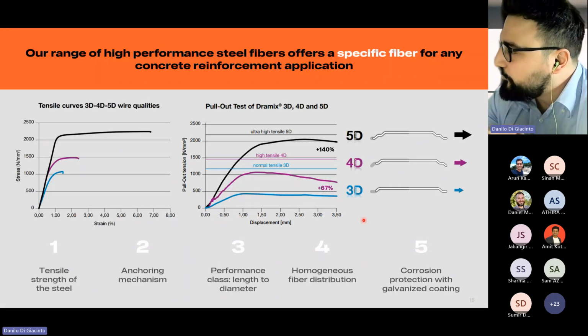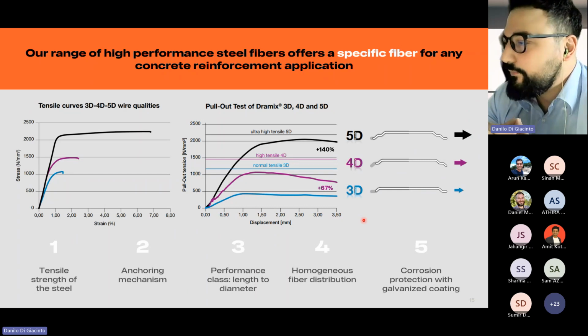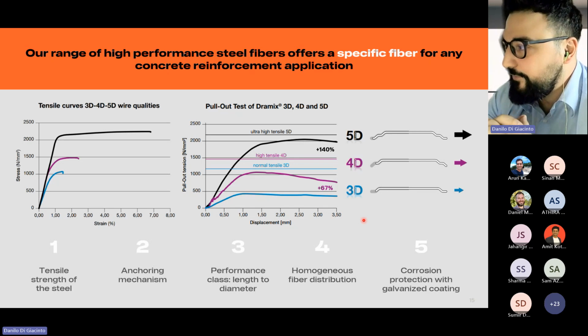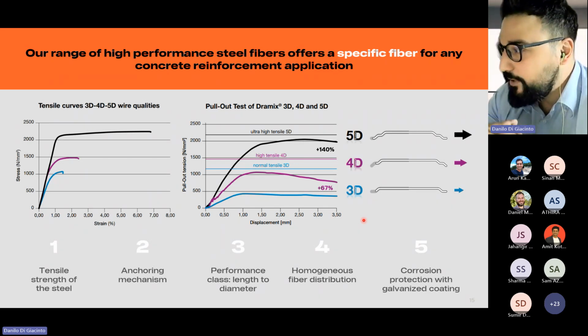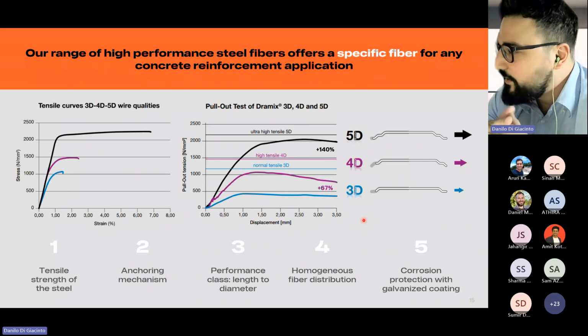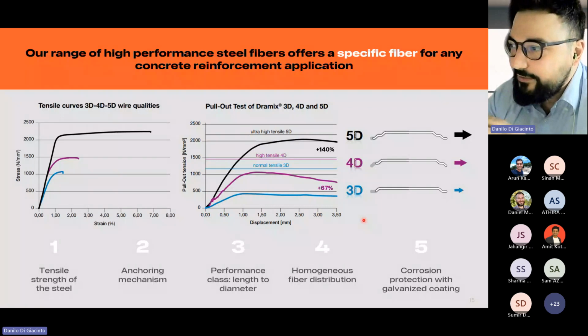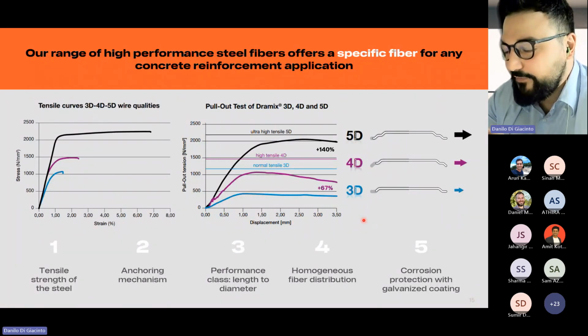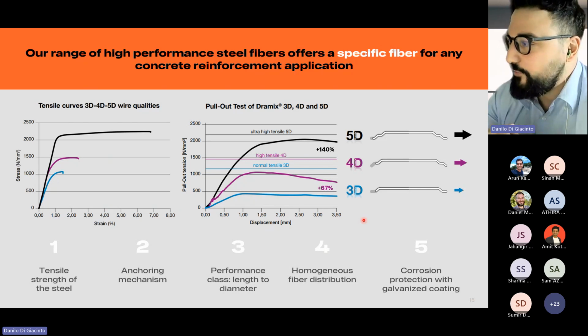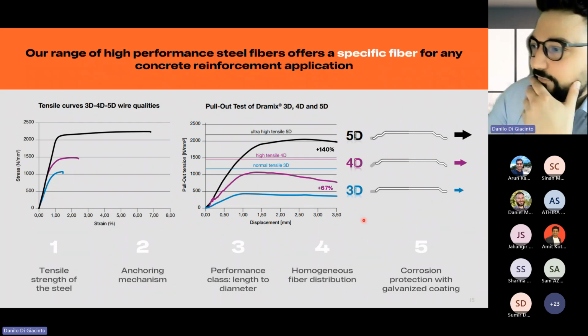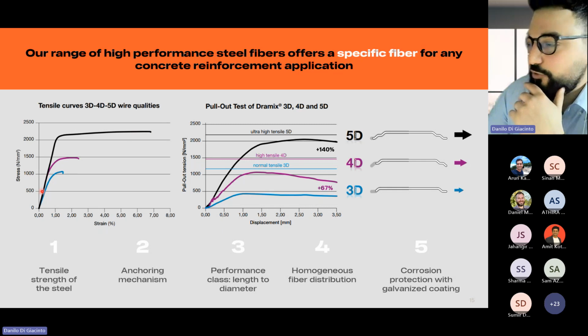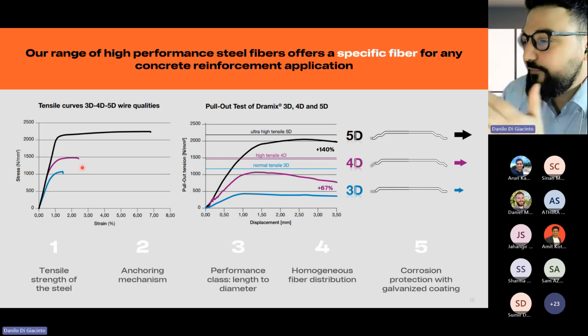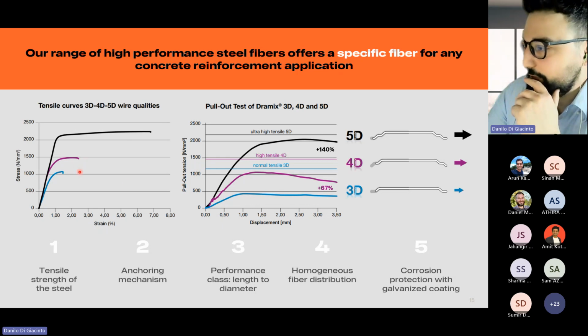Here, a lot of concepts, but to put it in a nutshell, I already talked to you about our fiber families, 3D, 4D, and 5D, but what changes when it comes to numbers? The wire strength is different. Obviously, an advanced fiber has a base wire strength which is higher than, for example, a 5D than a 3D. For 5D, we can achieve up to 2,300 MPa of wire strength. For a 3D, it is around 1,200. A 4D fiber has an intermediate base wire strength.